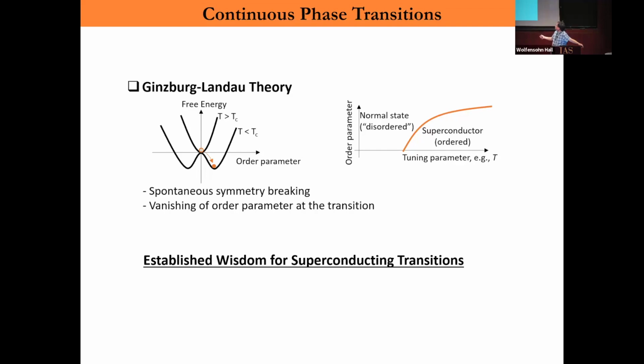So it's kind of disordered, not an ordered phase. Then with increasing tuning of the parameter, or decreasing the temperature, for example, we arrive at a superconducting state or the order magnet, where we have a finite order parameter. This type of phase transition is important. One important thing is that it breaks spontaneous symmetry, and this is how Landau characterized phases and phase transitions. The order parameter vanishes right at the critical point. So this is how we conventionally understand phase transition and superconducting transitions.